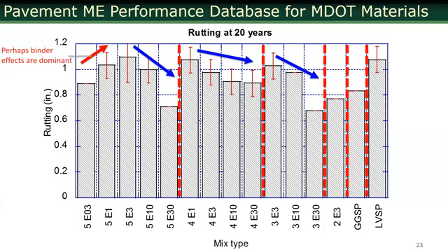But perhaps in this particular case, the binder effects are dominant. Remember, when you go up to 30, as you increase the ESALs, you're really having a lot more interlocking and a lot more compression between the particles. The effect of that is shown here, but at lower interlocking levels, perhaps the binder is overcoming it and there's no excessive rutting, which is good. That also shows that the overall Superpave system is working pretty well. The PG system is really not allowing excessive rutting, the binder properties overcome it.